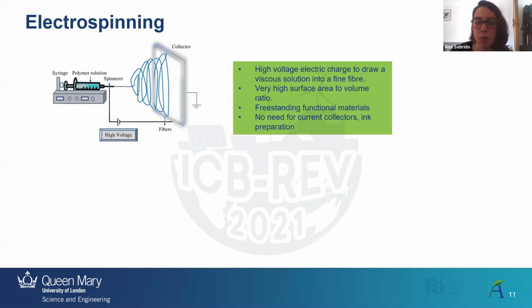For those who are not familiar with the technique, electrospinning is a technique that enables the formation of non-woven fibers by applying a high electric voltage between a metallic needle from a syringe, and a current collector that is also metallic, to establish the high voltage between those points. And inside the syringe, we're going to have our precursor solution, which will contain the main precursor of the fibers, the material that we want to prepare, lignin in our case.